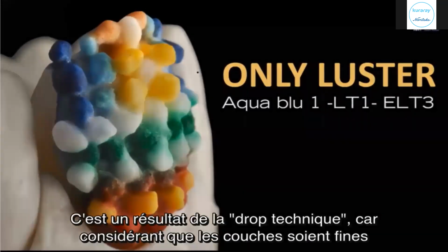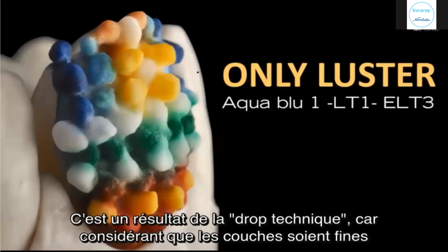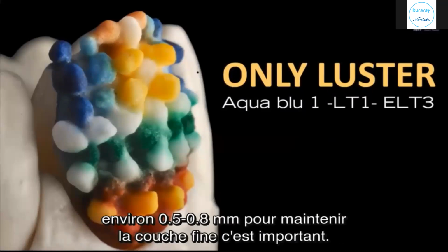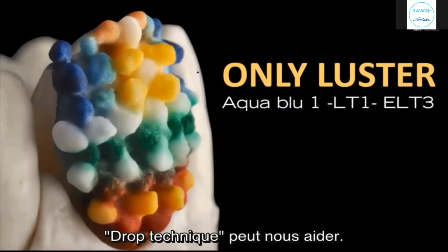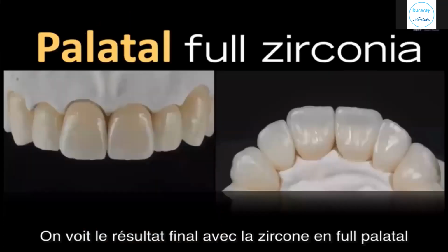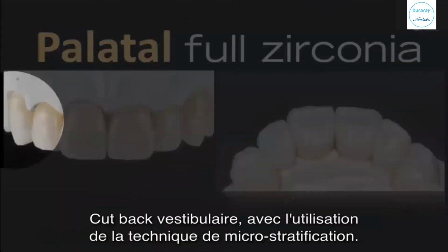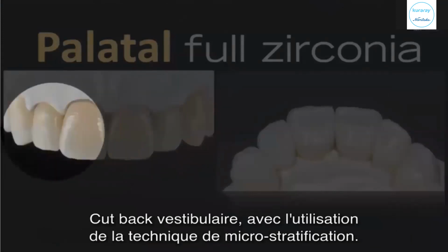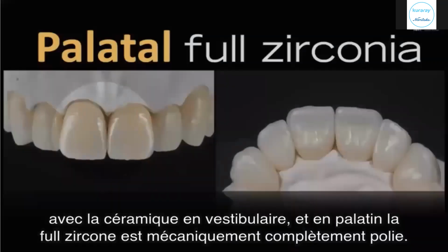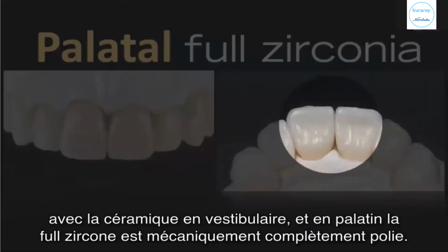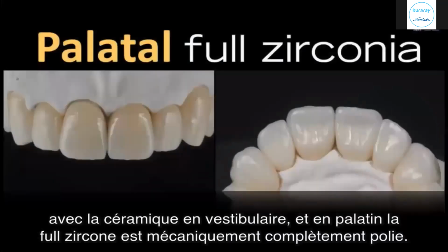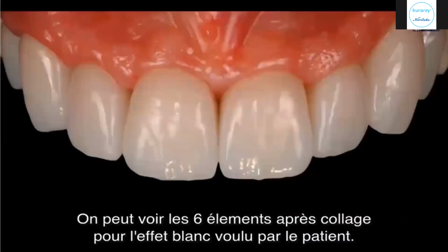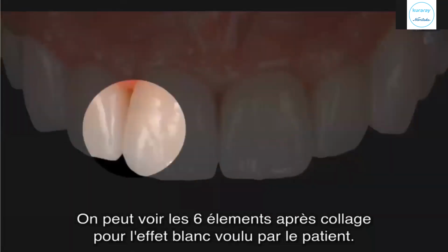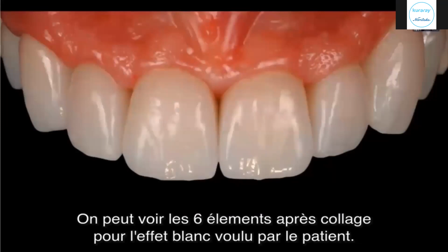This is the reason for the drop technique, because I consider the layer in a very thin condition, more or less 0.5, 0.8, and to maintain the humidity in a very thin layer is important. Drop technique could be a help for us. And we can see the final result with the palatal full zirconia, cutback vestibular, where we use the micro layer technique, with ceramic vestibular and palatally full zirconia, completely mechanically polished. And we can see the 6 elements after the cementation, with the white effect for the patient.